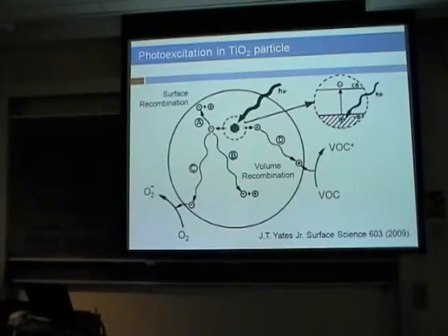Okay, so what's happening in a general photocatalytic reaction? When we get to water splitting, we'll put up a very similar kind of diagram. It will just be happening in the reverse direction. So let's say this is a titania nanoparticle, and we'll start with the surface reactions. We have a couple of reactions going on. If we're trying to decompose these volatile organic species, then we can reduce oxygen with electrons that are available on the surface. And this O2 negative, maybe this isn't the best diagram, doesn't really come off the surface. So it stays on the surface and it subsequently dissociates.